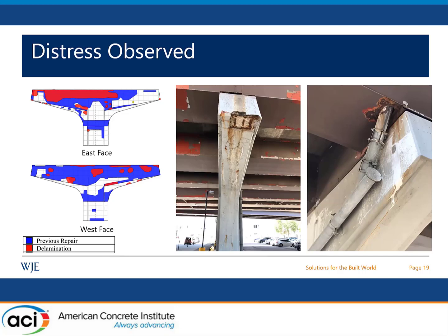You can see in the figure on the left that there were a number of delaminations occurring in areas that had been previously repaired in the 1990s, which suggests that the same root causes of the failing of the joints and also failing of the drainage system were causing a lot of the corrosion-related activity and chloride exposures we were seeing.